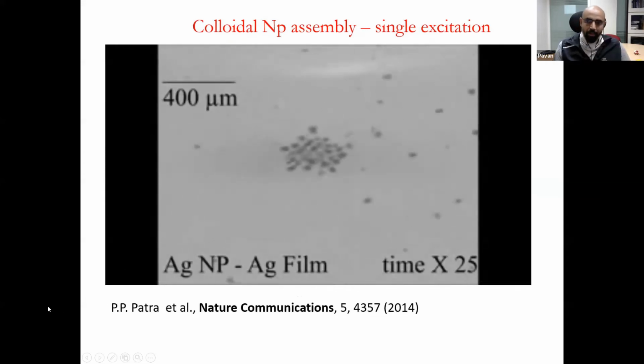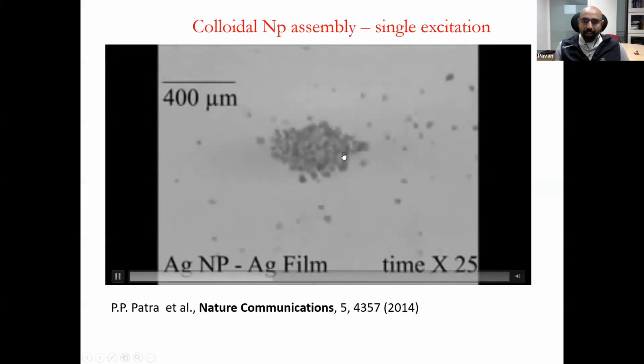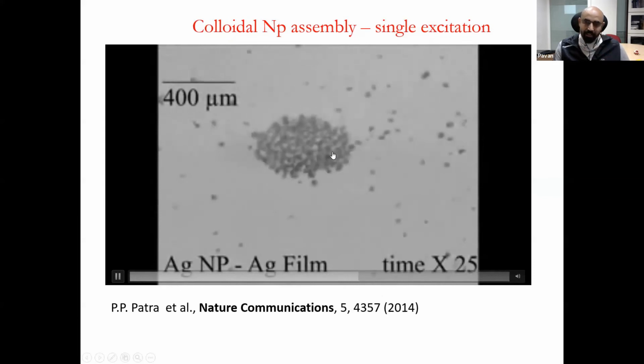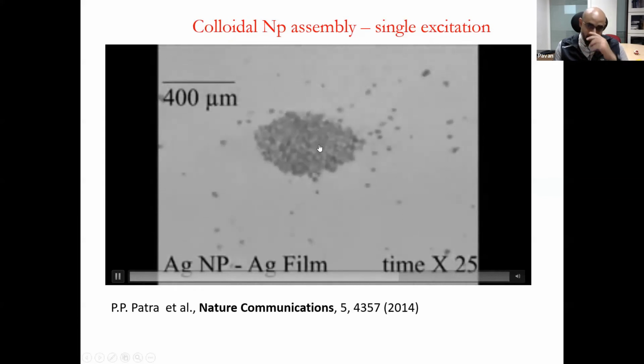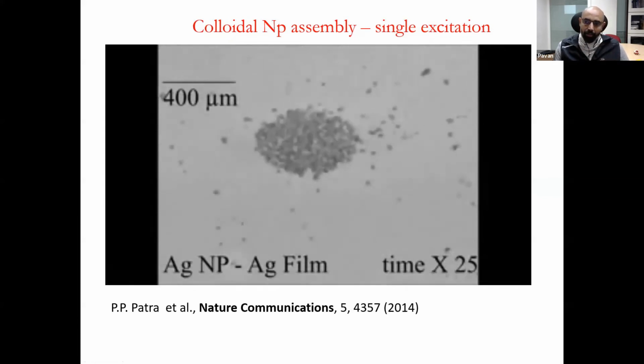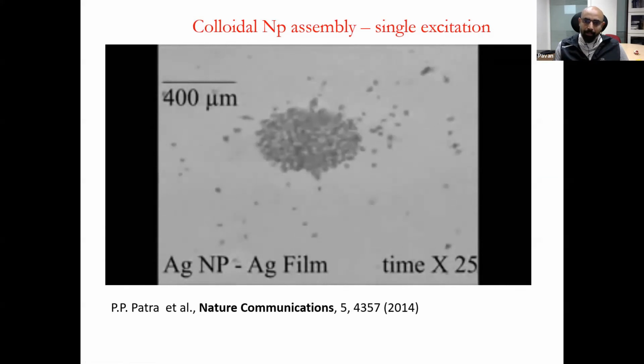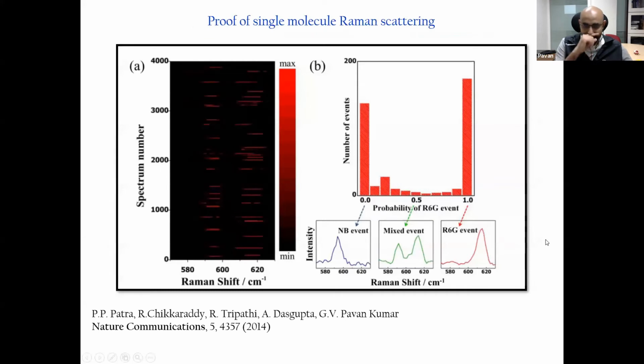So if you now excite the plasmon, what you are seeing is the aggregate of nanoparticles forming at the location of interest. These are bright field microscopy images. You can also utilize dark field images for visualizing such processes. What you're seeing is a swarm of nanoparticles which have assembled as a function of time.